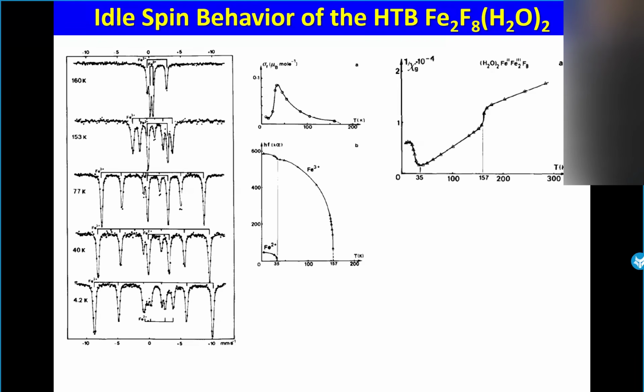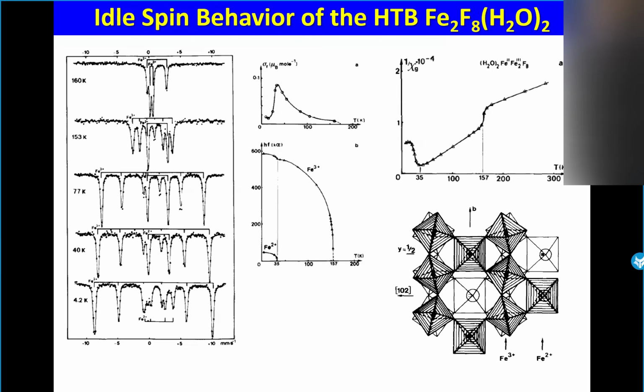Now, if we look carefully, what about the evolution of hyperfine fields? You have, in this case, an evolution here with a small cusp for iron 3. And you have the evolution of the hyperfine field of iron 2. And you can see that the Néel temperature of the iron 2 component corresponds to this cusp. Look at the inverse of susceptibility. There are two critical temperatures, corresponding to the blocking temperature. Why is this? The structure is like this. You have magnetic moments, and over a certain temperature, a magnetic moment does not know how to be blocked because there is a kind of competition. And when you decrease the temperature, finally, yes, it can block itself. And that is why it is idle spin behavior.